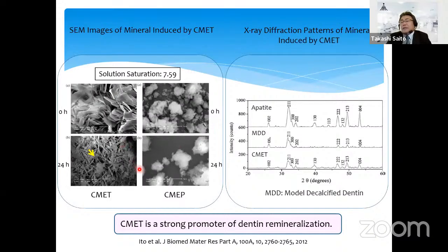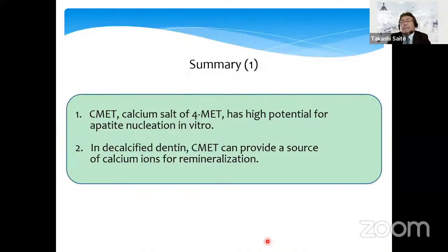The mineral crystals induced by CMET 24 hours after incubation in a mineralizing solution were plate-like crystals, and they were identified as apatite according to the X-ray diffraction pattern. Summarizing the result, CMET, the calcium salt of 4-MET, has a high potential for apatite nucleation in vitro. In decalcified dentin, CMET can provide a source of calcium ions for remineralization.